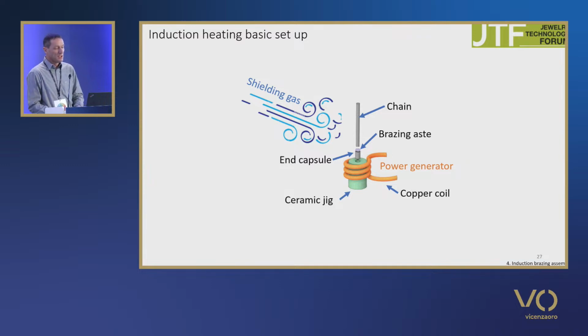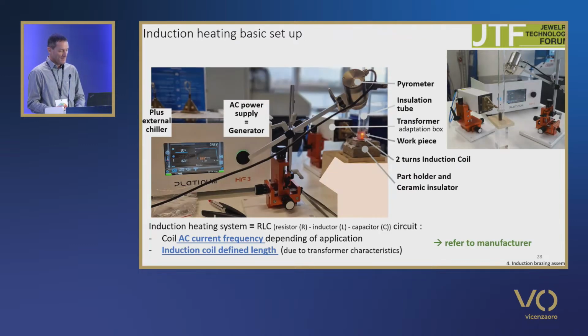So the basis of the induction setup is a power generator, an induction coil, and a ceramic jig, and if you need, you can add shielding gas. The equipment has an AC power supply, alternating current supply, and a transformer, that's the gray box. We add a pyrometer in order to follow the temperature, and you can see the workpiece at about 800 degrees. There are some key points to refer to the manufacturer about the AC frequency and the induction coil length.